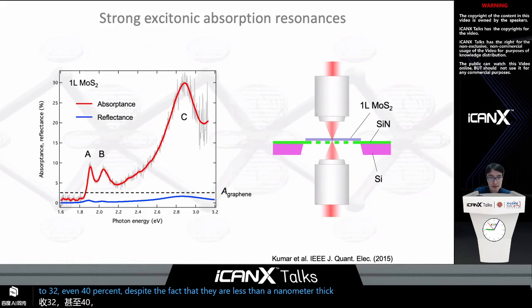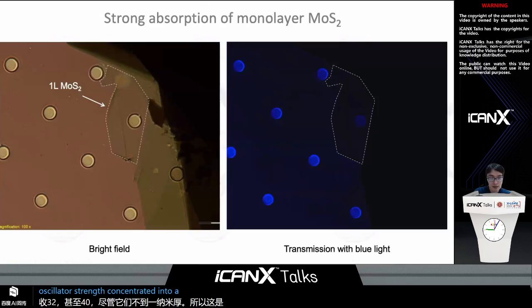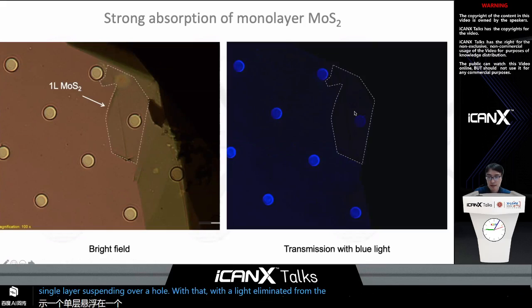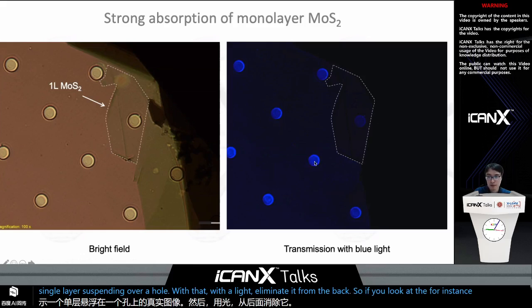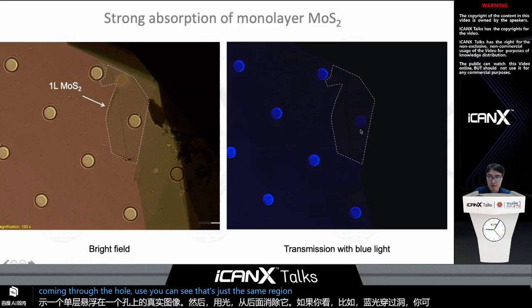So this is the result of excitonic resonances, or oscillator strength concentrated in these excitonic resonances. Here's another demonstration to show the actual picture of a single layer suspended over a hole with light illuminated from the back. If you look at, for instance, the blue light coming through the hole, you can see that just this single layer region will attenuate the light fairly well.